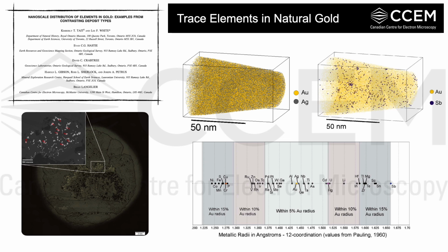Antimony-bearing minerals are common to many gold deposits that can form in a variety of temperatures and depths in the crust, but are more commonly found in shallow, low temperature deposits. The antimony within the McLaughlin gold is forming nanoscale domains that are heterogeneously distributed, and the metallic radius of antimony is just over 15% larger than gold, suggesting that it's too large to substitute within the gold lattice, or if there was antimony substitution, it has subsequently been migrated into domains through secondary processes.